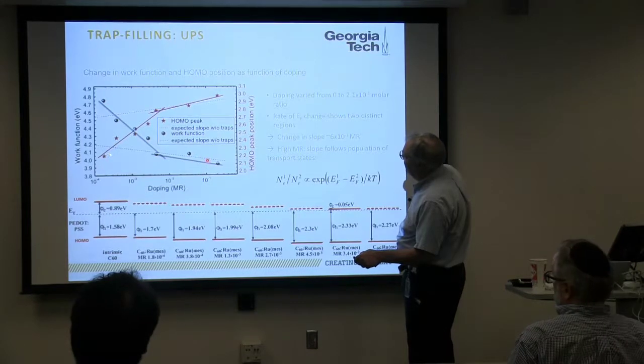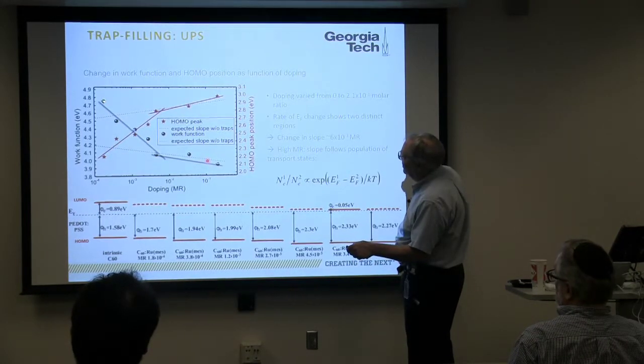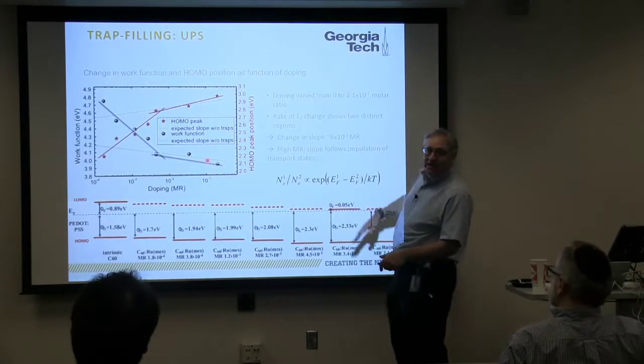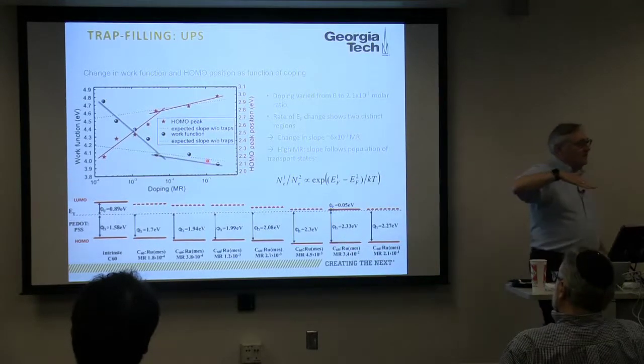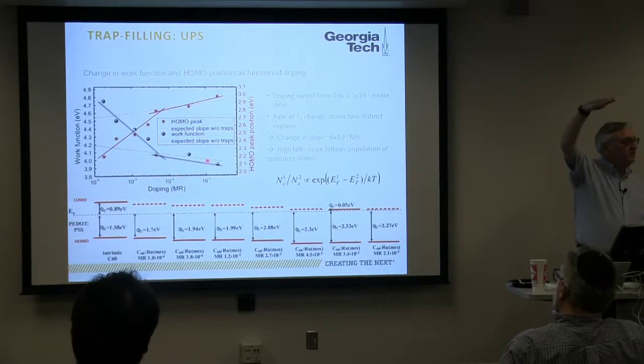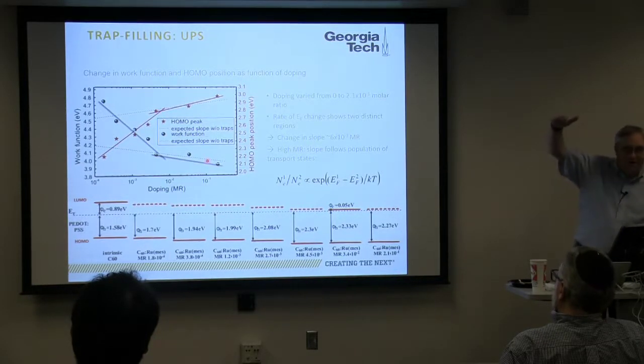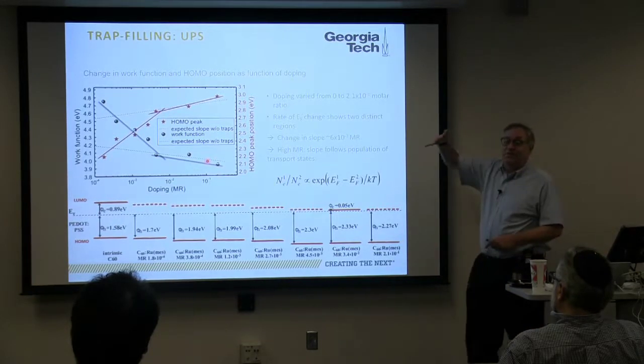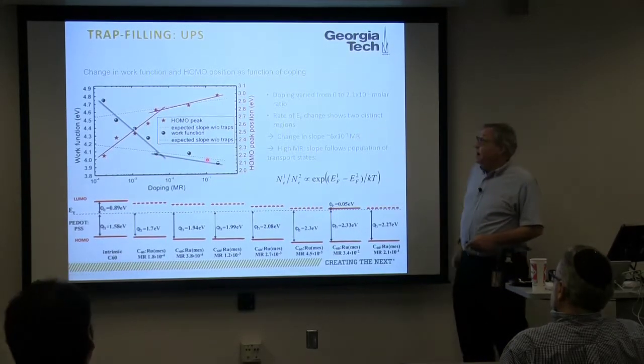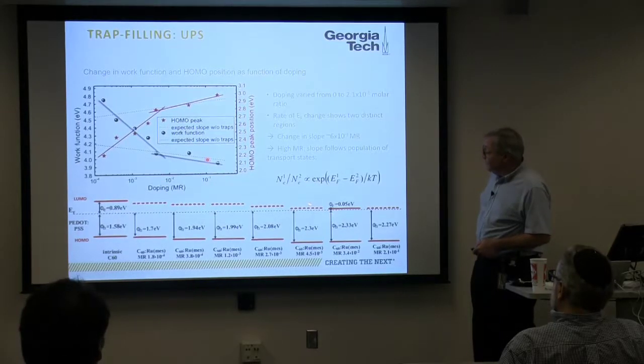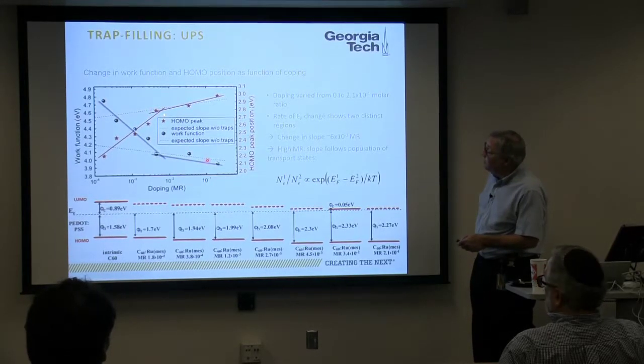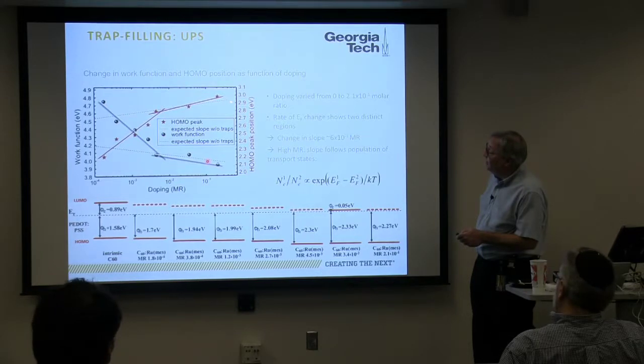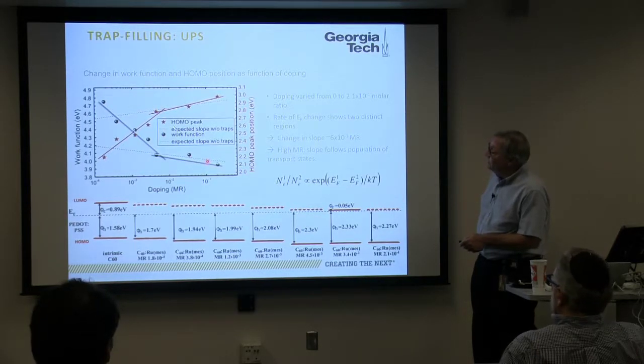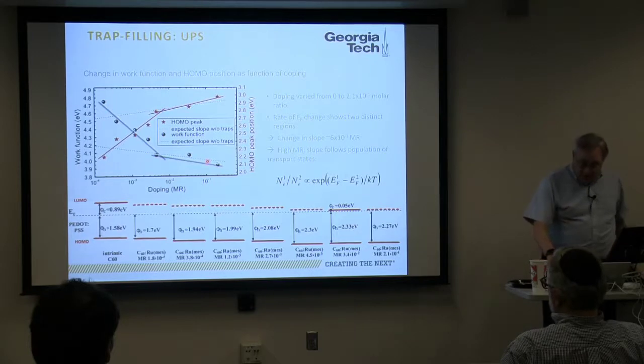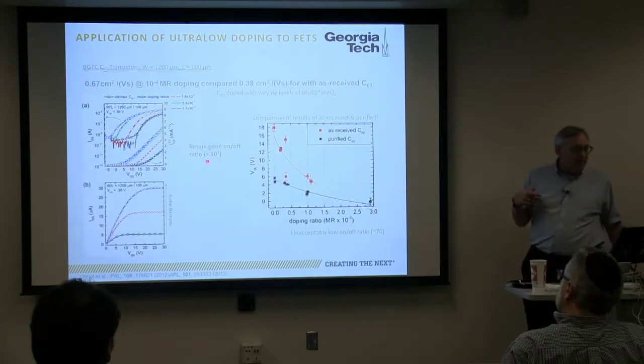One which has a steep slope and one which has a narrow slope. So what's happening is that in this low doping region, we're filling the trap states. There are very few of those trap states, so a very small number of electrons is going to lead to a large change in work function. But then when we actually begin to fill the manifold of the states where we're really reducing the molecule, okay, then it takes many more electrons to lead to a change in the work function, and that's what we see here.